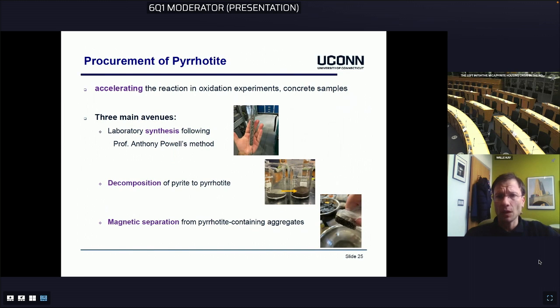One is producing our own pyrrhotite through pyrrhotite synthesis, following the method from Professor Powell, where we run through different temperature regimes, and we have been successful with this. Another method is decomposition of pyrite, which can be purchased, into pyrrhotite. Another method is magnetically separating the aggregates we received from the quarry, and in this case we can increase, and have done so, the total sulfur from 1% to about 8%, which also accelerates the reaction.